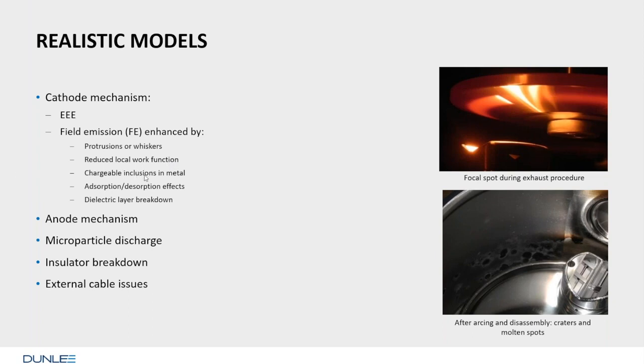Inclusions may pollute the surface. There may be some spots on the surface which are not pure metal, but chargeable inclusions. Also, adsorption and desorption of gas has an effect. A gas blanket, we will come to that, prevents field emission or provokes field emission. So that can also change the field emission.